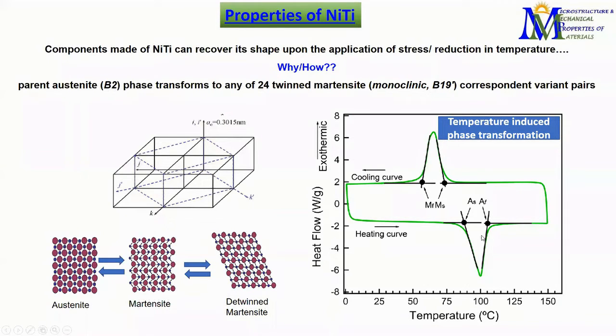So we have initially heated the specimen up to 150 degrees centigrade and then we start on cooling. And you can see that at one particular temperature, we are going to get a peak. So this is the martensite start temperature and we are getting a peak and which completes at a martensite finish temperature. And when we are heating it back, we are getting the austenite start and finish condition. Okay, so we can achieve the reversible austenite to martensite to austenite transformation if we are simply changing the temperature. Okay, and shape memory effect is partly related to this kind of temperature induced process.